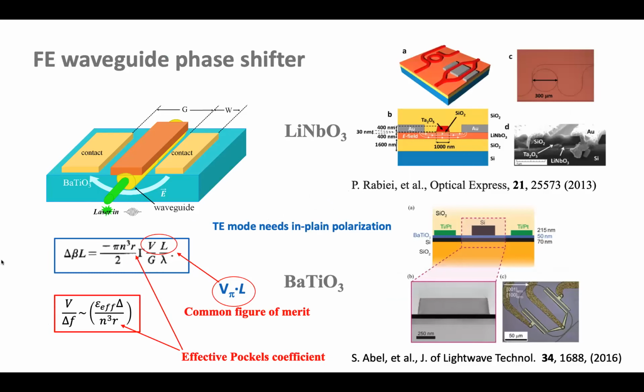First, you need to take barium titanate and confine light somehow. There are various ways of doing that. You can etch a ridge, or you can put something on top which has a dielectric constant difference. So you're trying to make the light go along this green line. You make a waveguide, and then you put contacts on top and apply an electric field. In this case, it will be parallel to the surface, so this only works for TE mode. That's a specific kind of design for the waveguide.